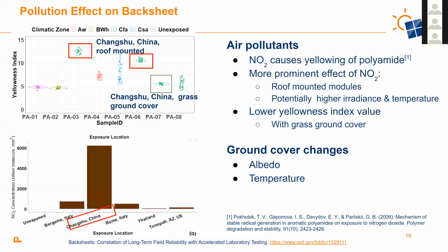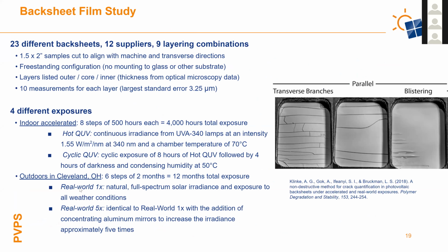And then we also put them outdoors in Cleveland with natural full spectrum light, and then with concentrators on them to increase the irradiance. And we got cracks that look like this on the back sheets, which are cracks that we see from PV modules as well.